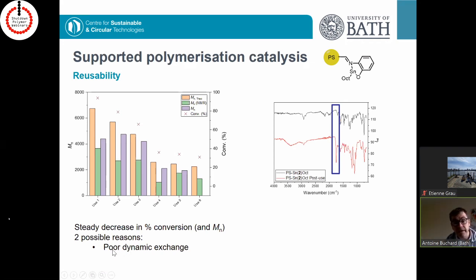The first one is there might be some poor dynamic exchange. Indeed, what we see when we reuse those catalysts, or when we analyze them post-mortem after use, is there's a clear band of PLA. So it looks like there's some PLA stuck, if you will, to the beads. It could be because we don't wash the beads well enough, but we have done this quite thoroughly, so we were not sure what was happening.